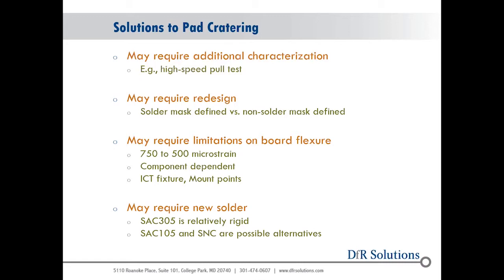The thing is, they break around the same stress values. So when you do a drop test or shock test, you'll see mixed mode. You'll see intermetallic fractures. You'll see bond pad cratering, sort of all mixed together. But really, what we're looking at for mitigation of pad cratering is limiting the amount of strain on your board during assembly.